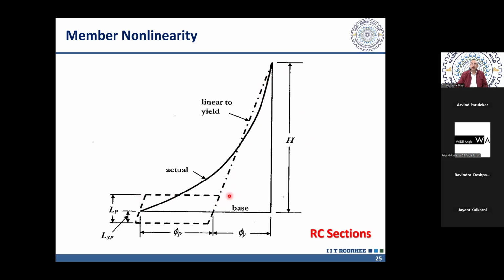So this is our equivalent bilinear curve, and we consider this equivalent bilinear moment curvature curve as consisting of two diagrams. One is this linear variation of curvature. So here we can see that the curvature is varying linearly up to yield, and whatever is the curvature beyond yield, that we lump in the form of this rectangular diagram at the base of this cantilever. So we call this the notional plastic hinge.